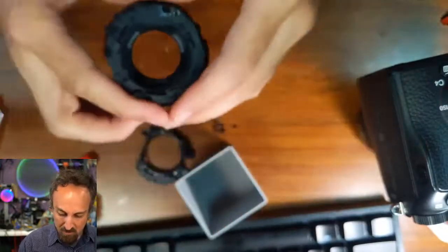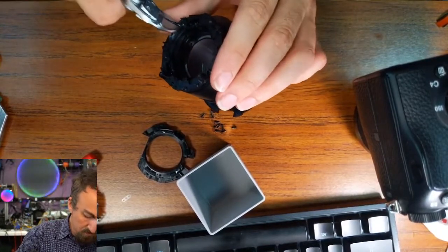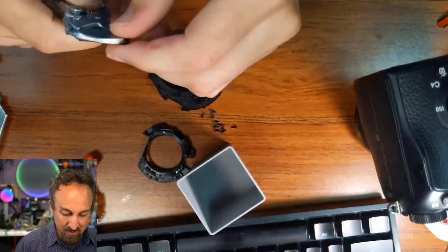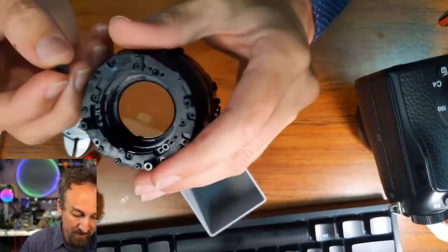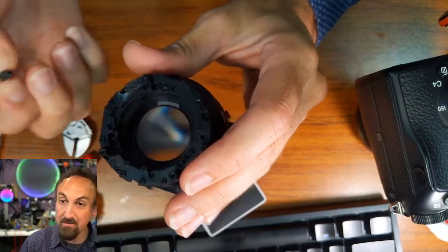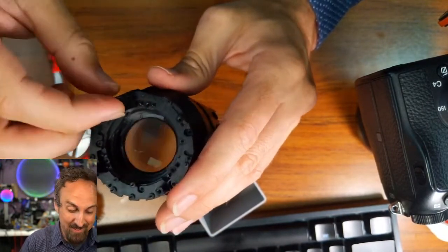Holy crap. Wow. It did not break the acrylate like this. I used cyanoacrylate. It did not break that. It actually cohesively failed the glass fiber reinforced plastic again. That's amazing. So I should have just glued it and went on. Moral of this story: that was a perfectly fine fix.